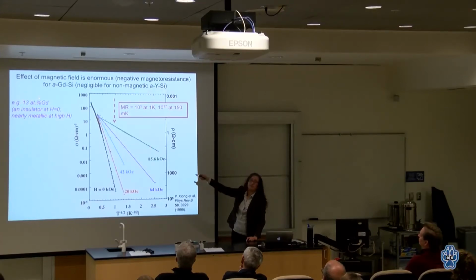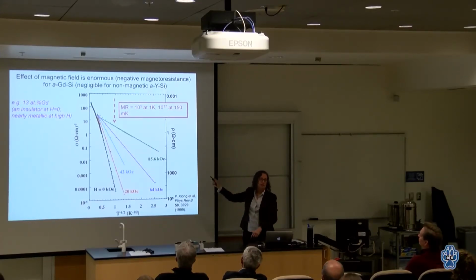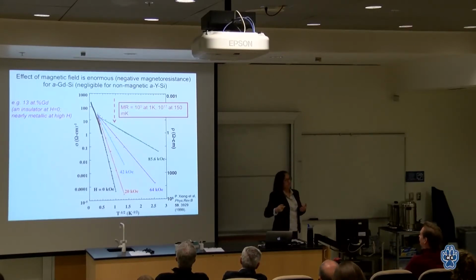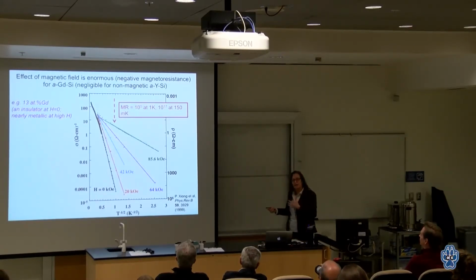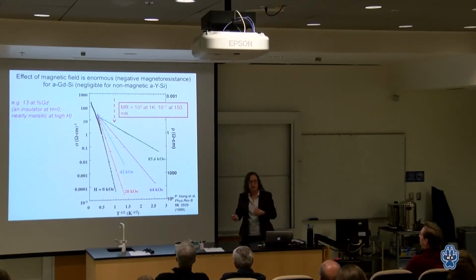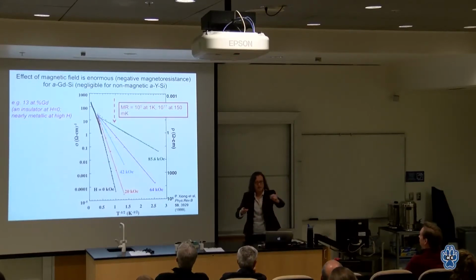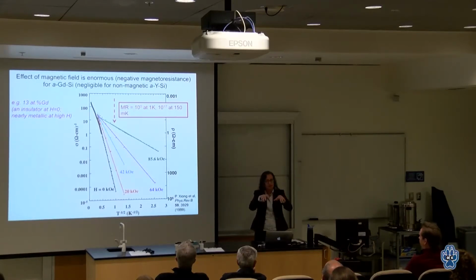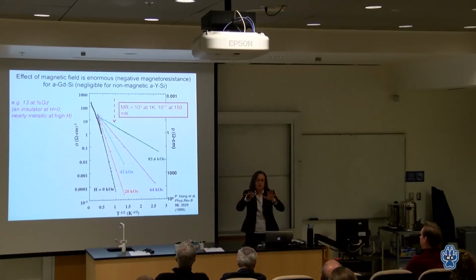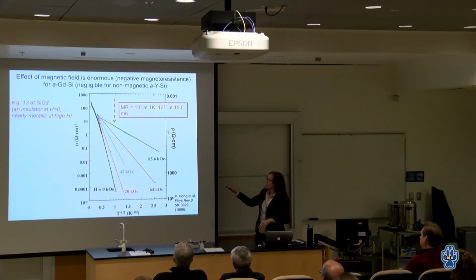And if I actually use 13.5%, I can go right through the metal-insulator transition. And all sorts of exotic physics happened. We had a way of studying the metal-insulator transition in a single sample just by varying the magnetic field. In a way, the simple way of capturing that is that the magnetic moments of the gadoliniums are all disordered. So it's like an extra source of disorder. And then when I apply a large magnetic field, they line up. So that disorder goes away. And that allows the electrons to move more freely. So I can drive a metal insulator transition in this material just by applying a magnetic field.